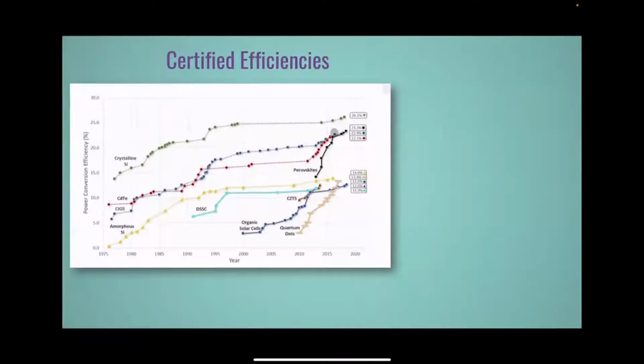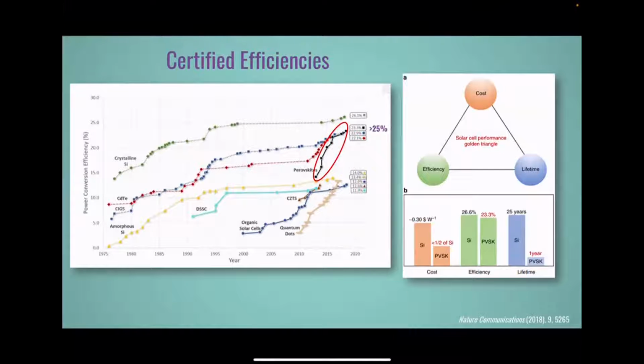They got just a few percent of efficiency, but in this cartoon you see here, in a few years from 2010 up to now, the certified efficiency of solar cells based on metal halide perovskites grew impressively, exponentially, and now we are at more than 25%. So you can see that in less than 10 years, the efficiency of perovskite solar cells grew in an impressive way. However, if you look at what is called the golden triangle of solar cell performance, these new solar cells based on metal halide perovskites have a very good cost with respect to traditional silicon solar cells. Also, in terms of efficiency, they are good.